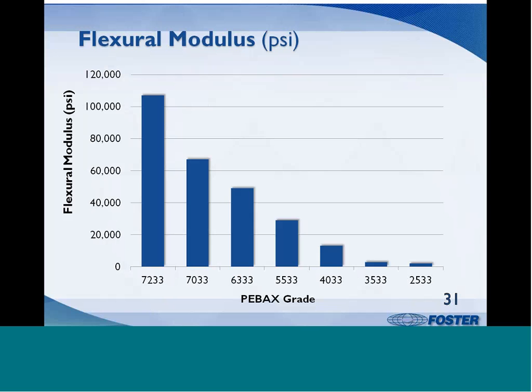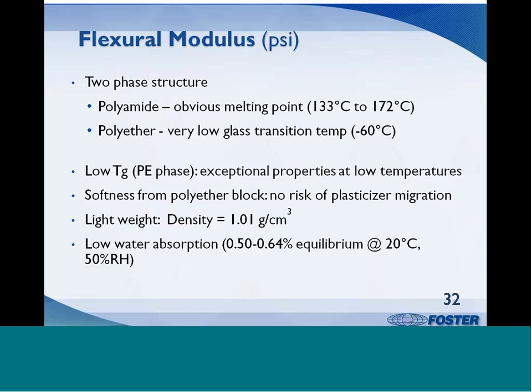Flexural modulus is very reflective of hard and soft block ratios. The hardest grades would be best for transferring torque, while the soft grades are appropriate for catheter tips, where it needs to softly sneak around corners without causing tissue damage. The key to a good block copolymer is having two components that are incompatible, but that phase separate to build a self-reinforcing morphology. In this way, the best of the hard and soft blocks can be taken advantage of.